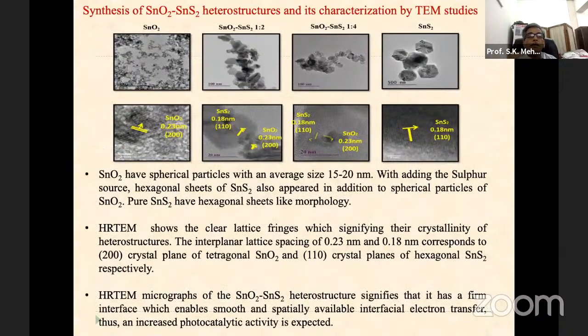A similar study was done on tin oxide nanoparticles and a combination of these two, tin oxide and tin sulfide heterostructures. Because when you form a heterostructure, we wanted to understand how the shape and particle size change. So tin oxide has spherical particles, as we know, and we have studied particles of 15 to 20 nanometer, but having a sulfur source in this, in the form of tin sulfide.